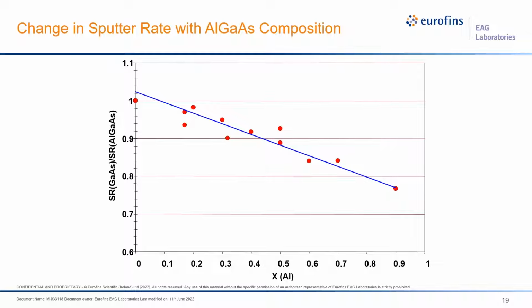The change in sputter rate between high and low refractive index layers in the DBR can be as much as 25%. PCOR-SIMS uses this empirical relationship between sputter rate and aluminum content to correct the sputtering rate for each data point depending on the aluminum content measured at each data point.